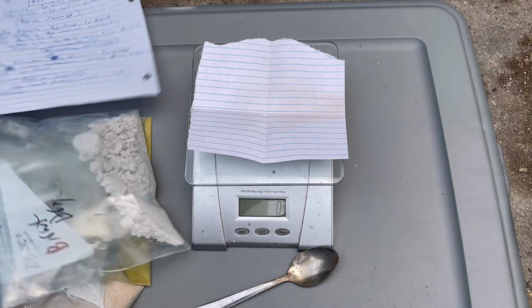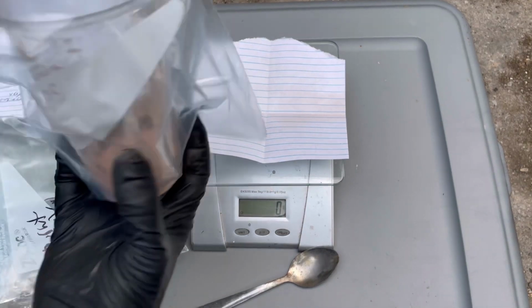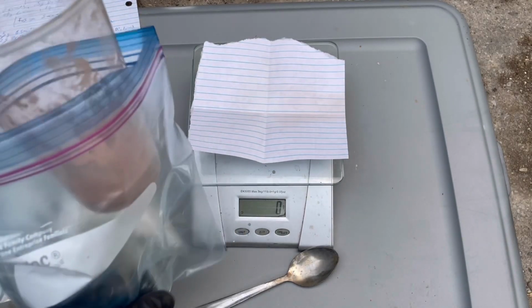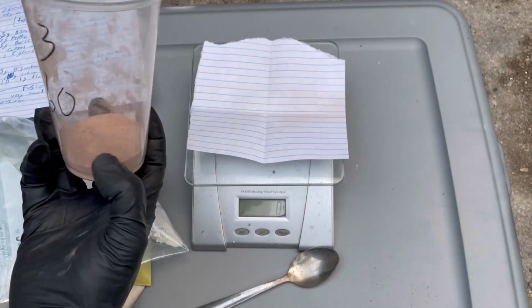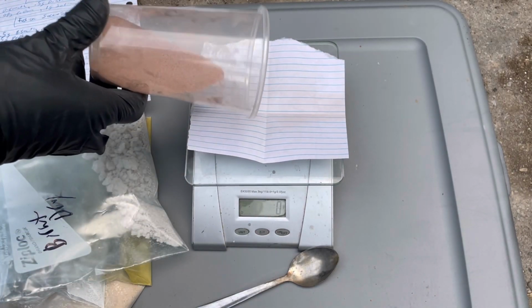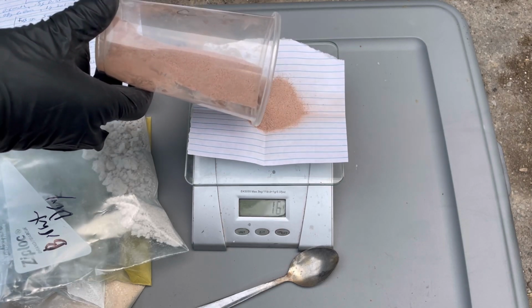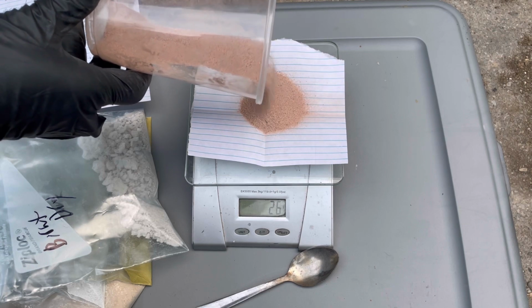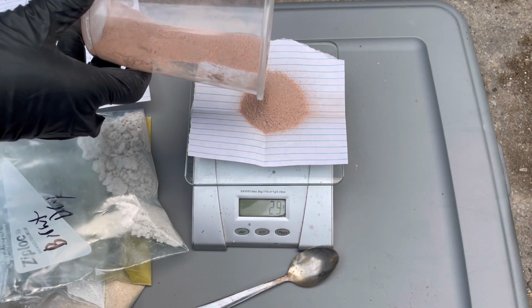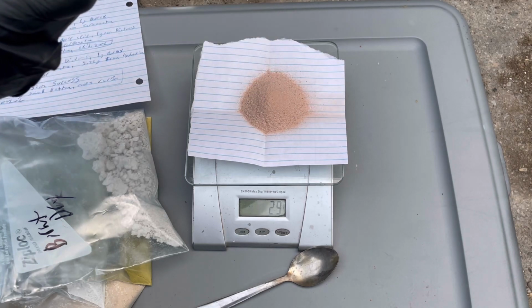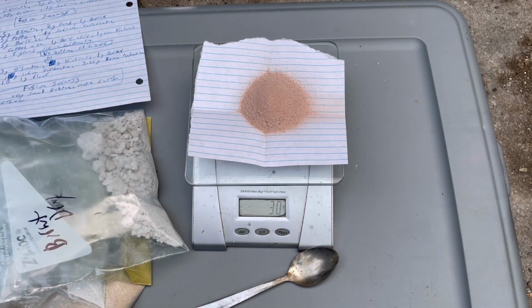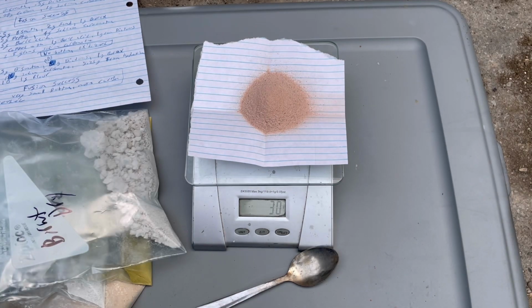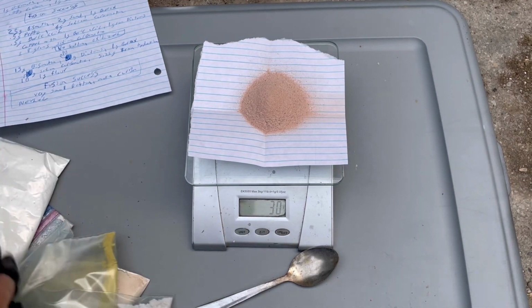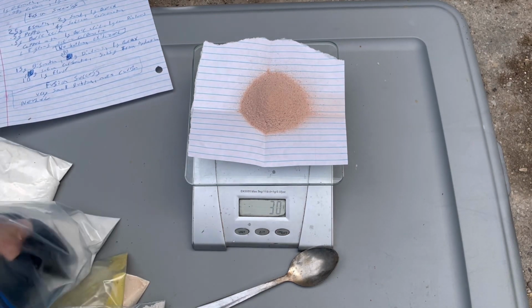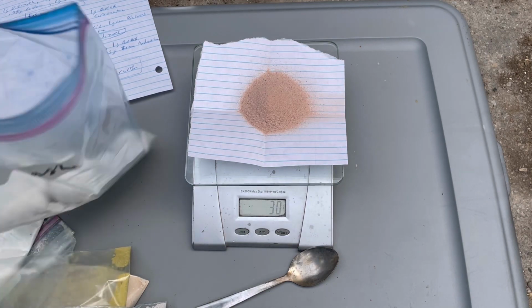So here's all the chemicals, got my notes handy, and here's the sample. Now you'll notice I've kept it inside of a plastic bag to keep air from getting to it, although with the silica, it doesn't really matter. Anyway, I'm going to weigh out half of the sample. That way I've got enough to try again if I have a failure. And also my crucibles that I made are really only big enough for a smaller sample anyway. There we go. So there's 30 grams of the silicate ore. Now this is essentially pure silicon dioxide. So to this, I'm going to add an equal mass, so another 30 grams of the sodium carbonate.